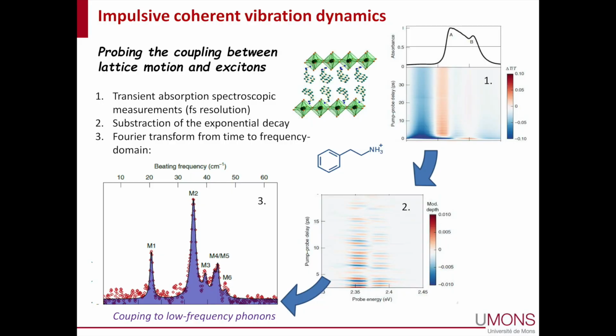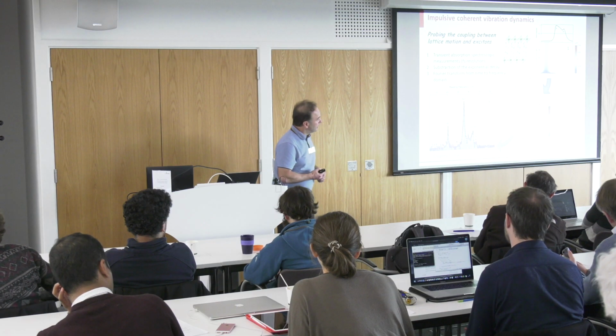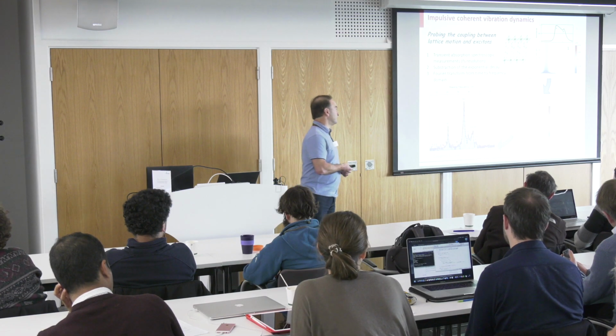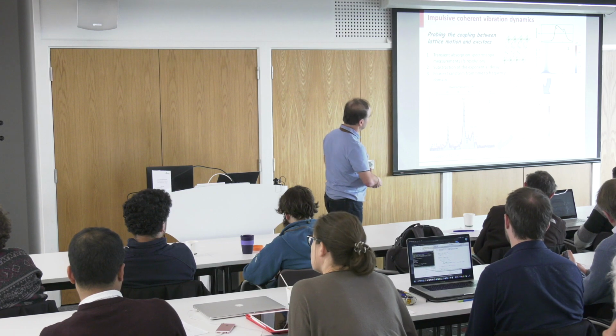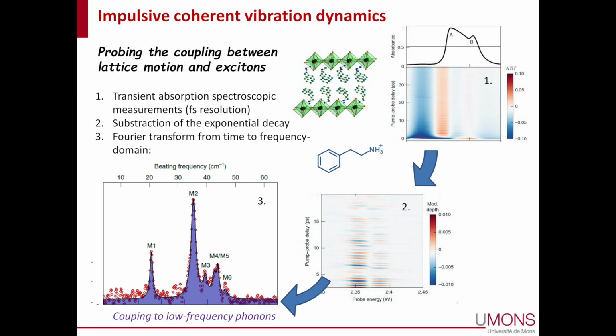This is work done by Carlos Silva on this 2D perovskite, where you see this is a pump-probe technique, where you can see bleaching and excited state absorption appearing, but on top of this population dynamics, you might also be able to see on this picture here that there are some fluctuations. And so those fluctuations, if you subtract the exponential decay due to the population dynamics, you can see them more easily here. And you can see these quantum fringes, which are due to the fact that you prepare in the excited state, hot states, you prepare a vibrational wave packet that then evolves in time, giving rise to these fluctuations. And you can Fourier transform this to know something about which are the vibrational modes, which are the phonons that matter. And you can see that those appear at very low frequency.